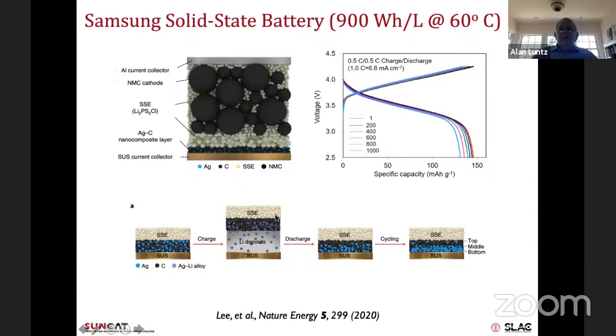Now I have to admit that although this looks great, there were a couple of experimental conditions that weren't practical for a real battery. One of them is they ran at 60 C, which is too high for a car battery. And the other thing is they applied a very huge pressure to keep the lithium as non-rough as possible. And that also is probably not practical.